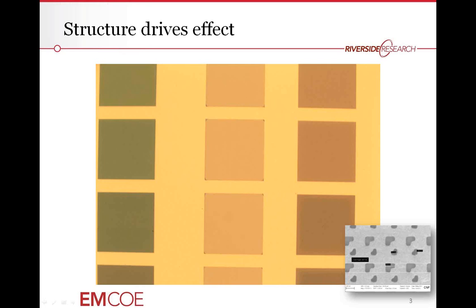So an illustration of the fact that it's the structure that drives these unique effects, rather than the material. Here, this is a micrograph, just a microscope picture, of a gold-coated chip. Everything you see here is gold. The only difference between the gold and the green gold and the pink gold and the reddish-brown gold on the right is the pattern that these things are patterned in. These are all, if you look on the bottom right, this is an SEM image of what these structures are. It's two L-shaped structures interspersed. And the difference between the green, the pink, and the red is basically the periodicity, the shape, slightly different properties in terms of the pattern in each one. But everything you see here is gold, and the difference in the optical response and the color is due to the fact that each one has a slightly different unit cell and periodicity structure.